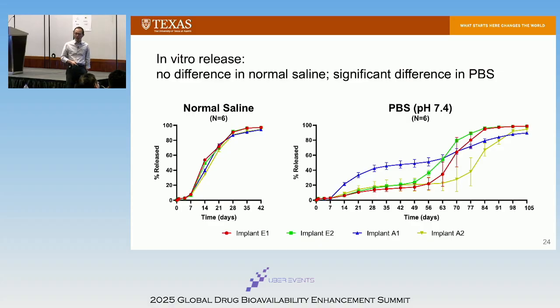Normal saline, they're all the same, right? If you look at the PBS, those two, this green and red, those are 2 different batches from Evonik, a year apart. 2 different students did it. And this is actually very consistent. We're looking at release over 3 months, right? This is more blocky, and this is less blocky. If I don't look at the Evonik material, this actually sort of trends with what we originally thought. More blocky ones, drug release is faster. Less blocky ones, it's a slower drug release.